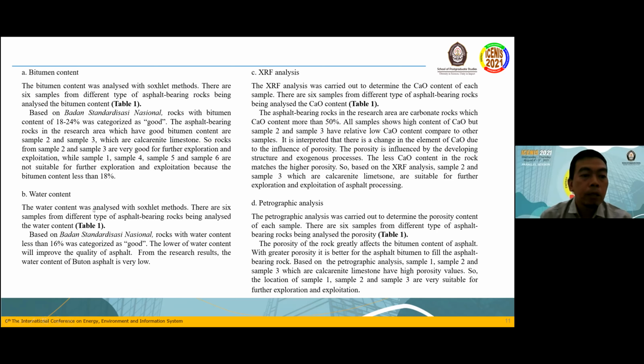Then the water content. Based on Badan Standarisasi Nasional, rocks with water content less than 16% were categorized as good, and all samples from the research area have less than 16% moisture content. So the water content of Buton asphalt is very, very low. Then from the XRF analysis, which is to analyze the CaO content, all the samples have CaO content of more than 50%, and it is related to the porosity, in which less CaO content in the rock matches higher porosity. So based on the XRF analysis, sample number 2 and number 3, which are calcarenite limestone, again are suitable for further exploration and exploitation of asphalt processing.